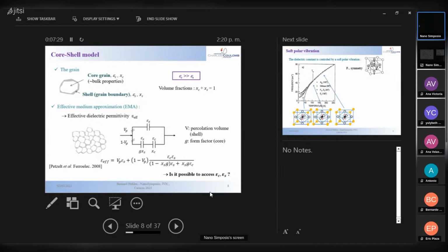And what says the effective medium approximation? If you build a ceramic from these grains, then for the current to go through the ceramic, you have two different ways. The one way is where the current goes through the shell. So that's what we call the percolation volume of the ceramic here. And so there you just have one capacitor, which is the capacitor made of the shell. And if you go directly through the rest, you have two capacitors in series, the shell and the core. Okay. And that's a parallel circuit.